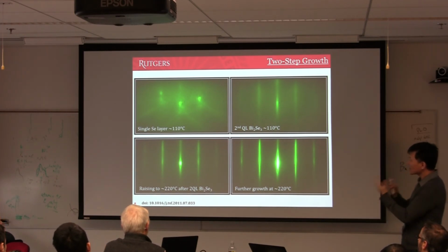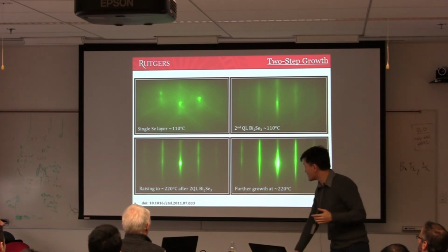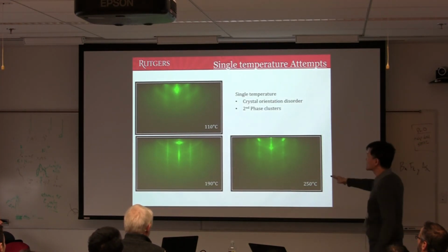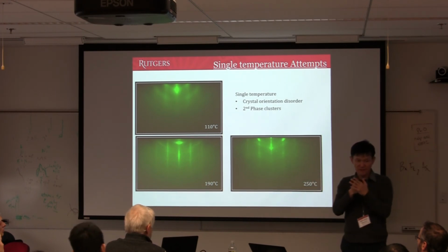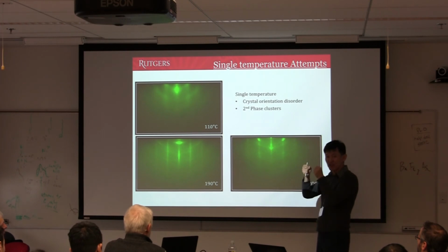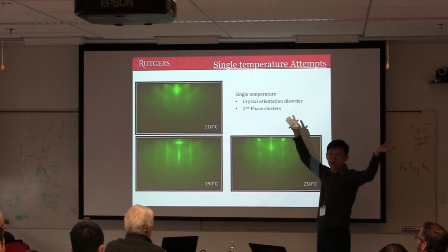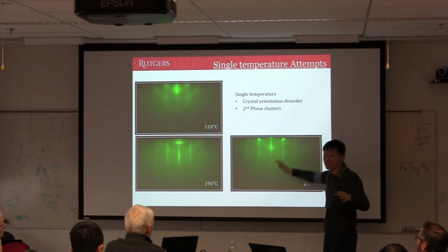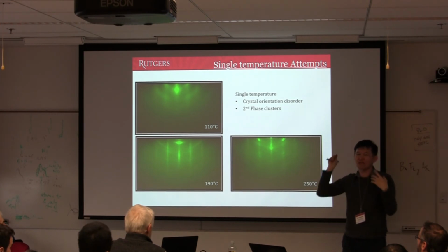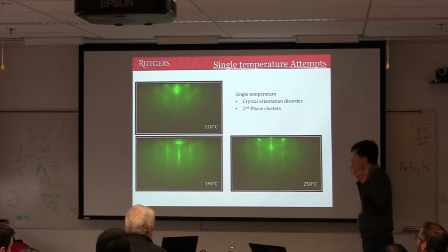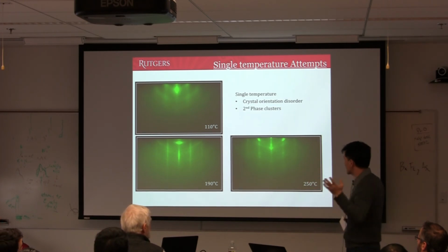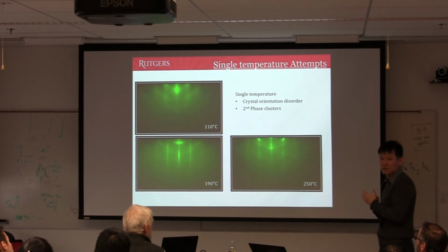What was happening is, once you form it, you cannot get rid of it. That means it reacted. Usually, if it is simply a 3D cluster, if you heat it up, you can evaporate it away and start over. But for this, it reacted, so you cannot get rid of it completely. It's all reacted. That makes sense because selenium is so reactive.